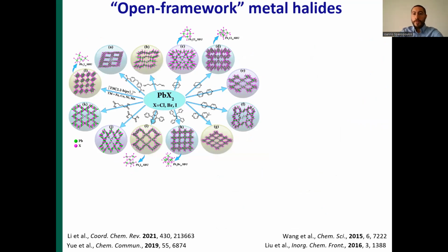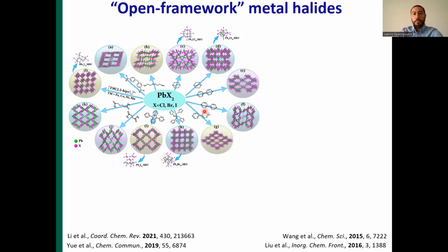So how can this be achieved then? How can we generate porous metal halide semiconductors? There is a very big recent family of metal halide materials, the so-called open framework metal halide materials, where the utilization of specific organic countercations, bulkier than methylammonium and formamidinium, can give rise to specific framework architectures with cavities, channels, and different types of pores.